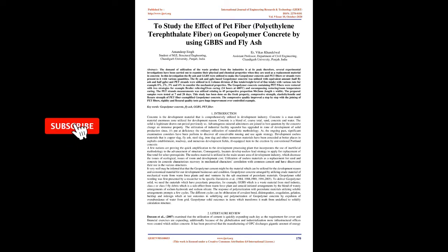The PET strand dimensions used corresponded to an aspect ratio of 45, 90 x 2 mm, length x width. The prepared samples were tested at 7 and 28 days. This study has been done on the fresh property, compressive strength, tensile and flexural strength of PET fiber reinforced geopolymer concrete. The compressive strength improved step by step with the addition of PET fibers. Tensile and flexural strength tests gave huge improvement over the control sample. Keywords: geopolymer concrete, fly ash, GGBS, PET fiber.